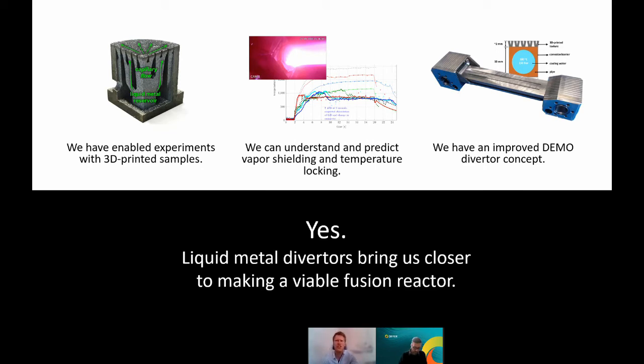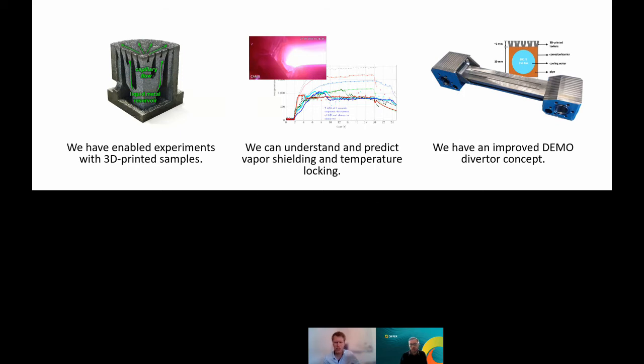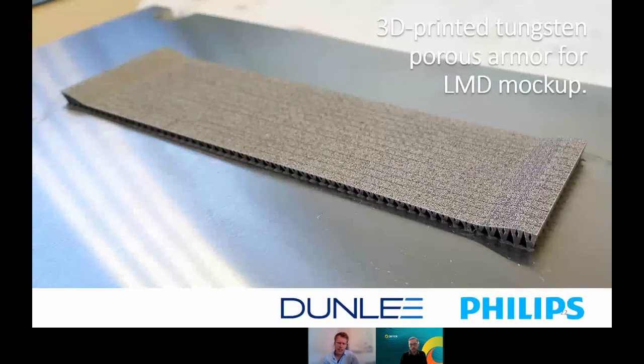There are actually two things that you need to take care about when you are designing the CPS. And flow speed is actually not number one. What you want to take care of first is flow stability. So you have to design the geometry such that the liquid can flow through smoothly without bulging out at any point. So we tested this with just a water flow experiment. We printed a bunch of plastic geometries, actually with a student, Joop, who did fantastic work on this. And that is why we selected the geometry that we have. The geometry is just a really rectangular array of these little tree-type structures. So I'll show you again. The channels in between these that go through this array are pointed perfectly vertical. And there you have very smooth flow, and the space in between just gets filled up with capillary forces. And that's the most important thing.